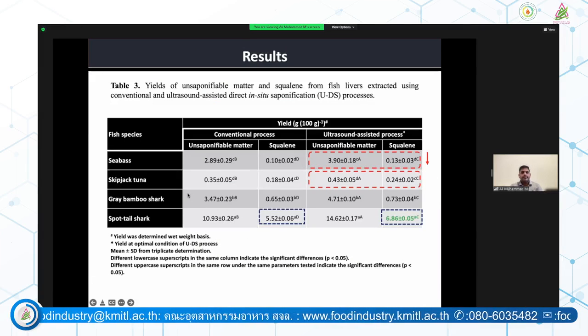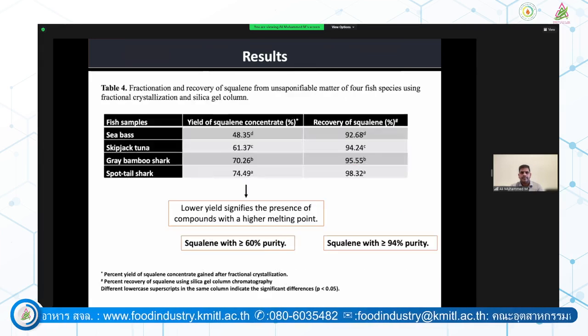Here is the extraction yield in the conventional method. As we can see, the extraction yield of oil is very low in the conventional method, and in ultrasound-assisted extraction the quantity of oil significantly increased, and the amount of squalene also increased, with the least utilization of solvents, time, and process steps such as filtration and centrifugation.